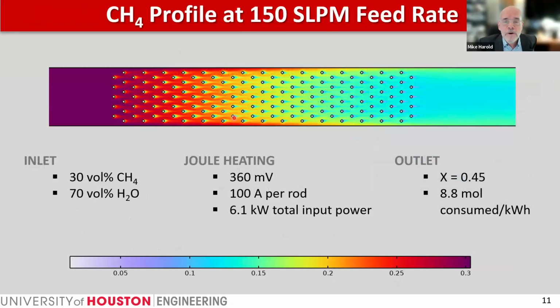This is the methane profile in this 100+ rod reactor where we are supplying nominally 100 amps of current per rod, given a total power input of 6 kilowatts. That's converting about 45% of the methane, and this shading shows the consumption of methane from left to right. You can see the little plumes around each wire showing the gradients of methane in the vicinity of where the reaction is happening. So the reaction only happens, and that's an assumption, on the catalytic layer.